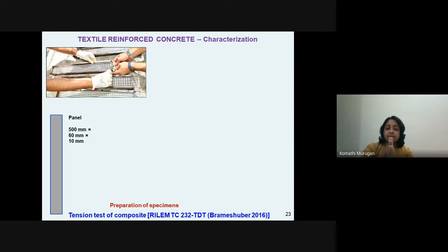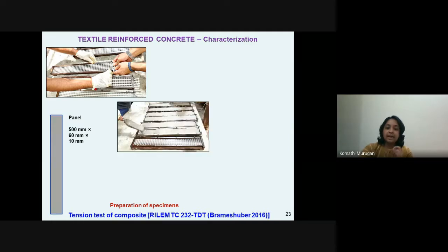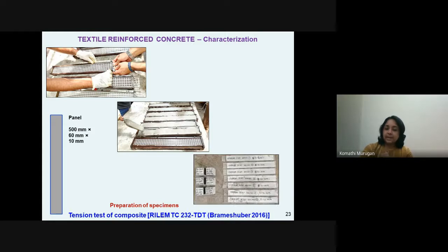For example, whether these are stiff textiles or flexible textiles, we don't want these textiles to sag, because these elements are very thin. Like say these elements are only 10 mm thick. So if we are checking the composites with 2 or 3 layers of textiles, we don't want these textiles to sag. So there are specific molds engineered for this purpose, where layer by layer these textiles are stretched and fixed in the molds, and the flowable type of concrete is poured to prepare these panels, which are used for the composite characterization.